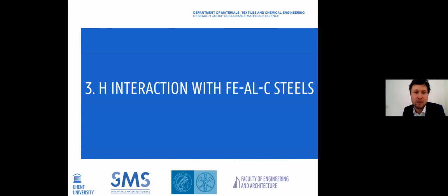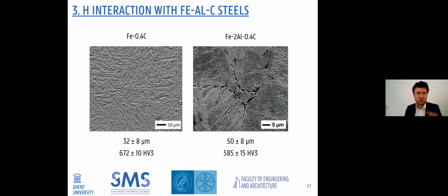I will move now to the aluminium addition. So in this case, we add aluminium to it. For the 0.4 carbon steel, we have the same microstructure, but in the case of aluminium, we see a change at the interface between the different grains. We see some opening, some delamination. We didn't know it was present there.